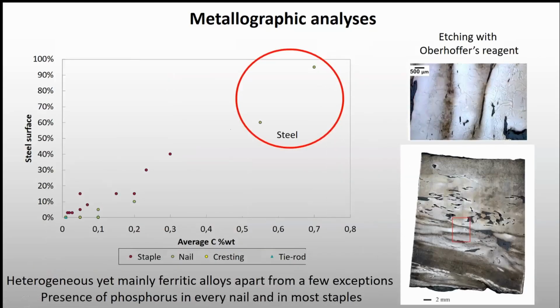If you plot the surface of steel observed on each artifact, you can see that 2 out of the more than 30 artifacts that were studied are actually made of real steel, and the others are either heterogeneous, and most of them are actually ferritic. But ferritic does not have to imply what would nowadays be pure ferrite iron, because most of this iron also contains a high content of phosphorus, which can be evidenced here by etching with another reagent, Oberhoffer's reagent, which reveals the difference here.